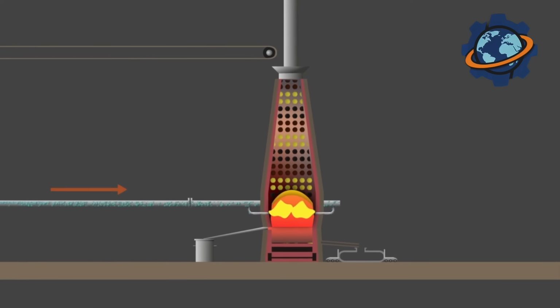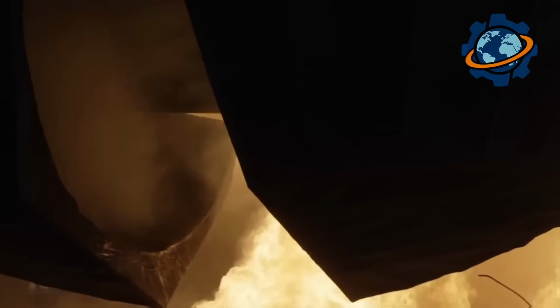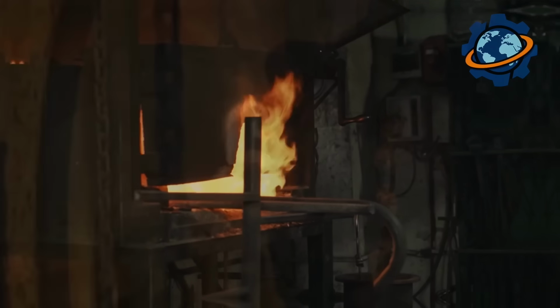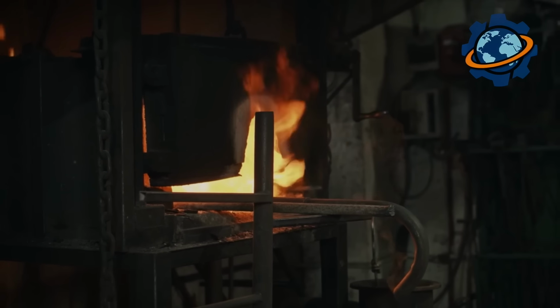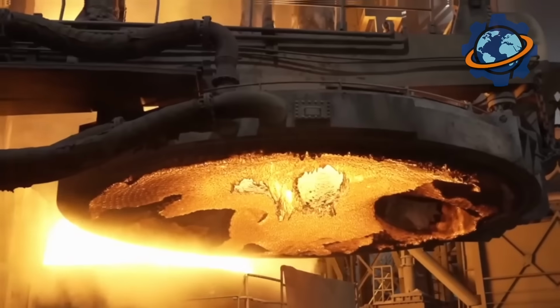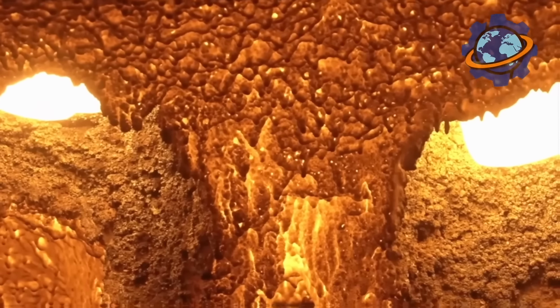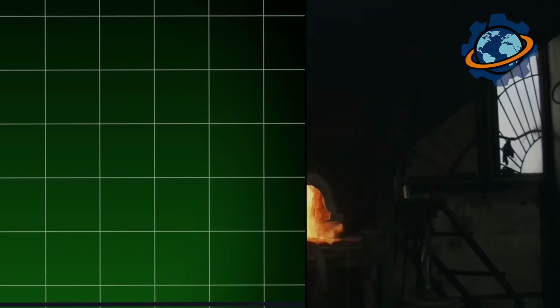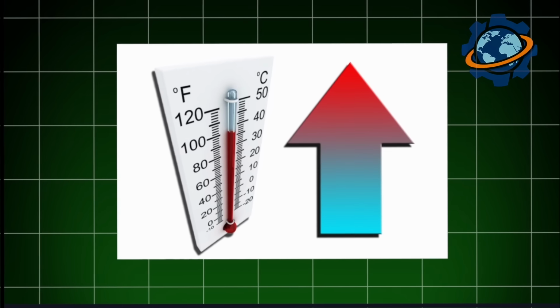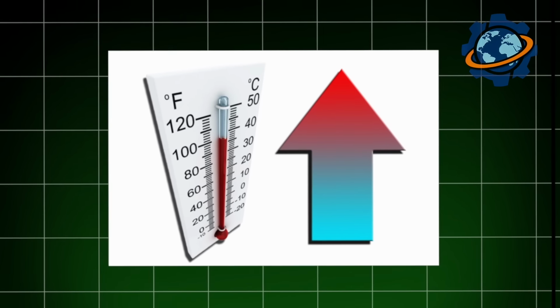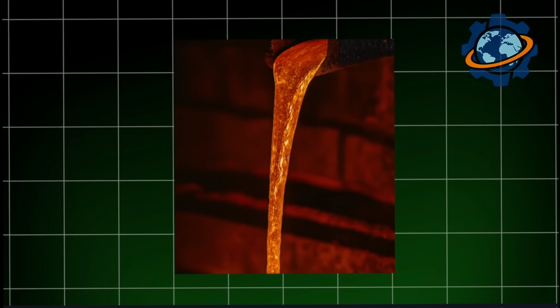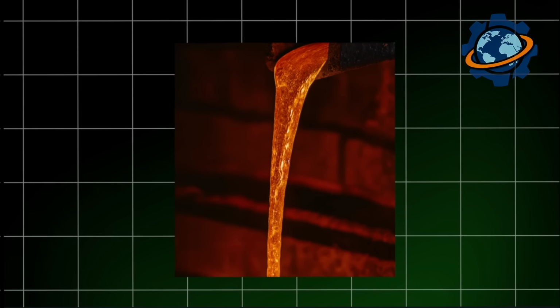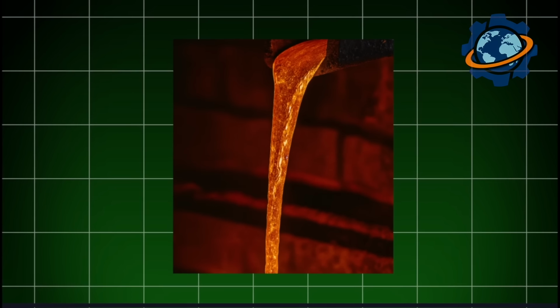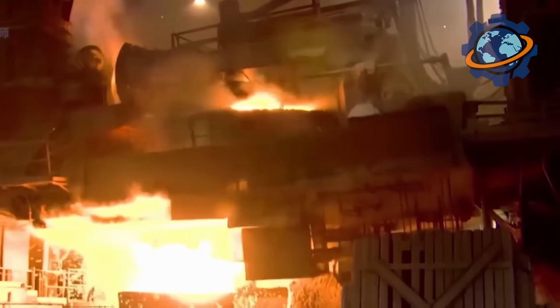The proportion, 3 parts oxide to 1 part coke. This mixture is loaded into vertical retort furnaces, steel towers 50 feet tall, lined inside with refractory silicon carbide. Heating begins. Temperature starts climbing. 1,800 degrees, 2,000 degrees, 2,200 degrees. At 2,200 degrees Fahrenheit, carbon begins taking oxygen away from zinc oxide. A reduction reaction occurs. But something amazing happens.